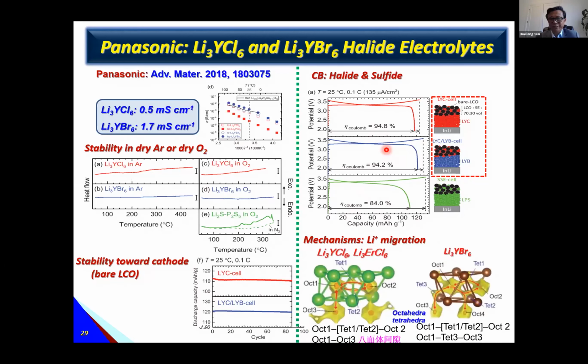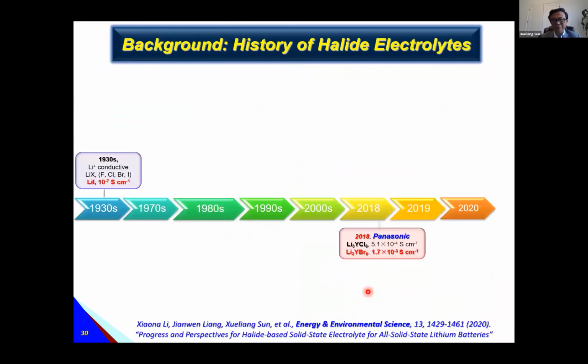And also the lithium transport mechanism is here. They found why they maintain very high ionic conductivity: the transport goes from octahedral to tetrahedral directly, or octahedral to octahedral, in the structure. That's why it maintains a very high ionic conductivity. And also talking about ionic conductivity, recently we have a summary of this field.